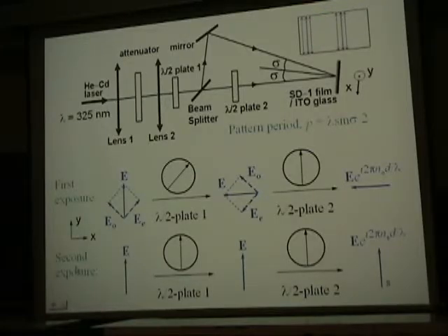where there should be little azo-dye alignment. Now in the second step, we rotate the optical axis of the first half-wave plate to vertical, and that returns the UV polarization to the y direction. And with that, when the first split beam passes through the second half-wave plate, it acquires a phase given by this exponent. Because this is a half-wave plate, the difference between this phase and the phase that we acquired in the first step should be exactly pi.